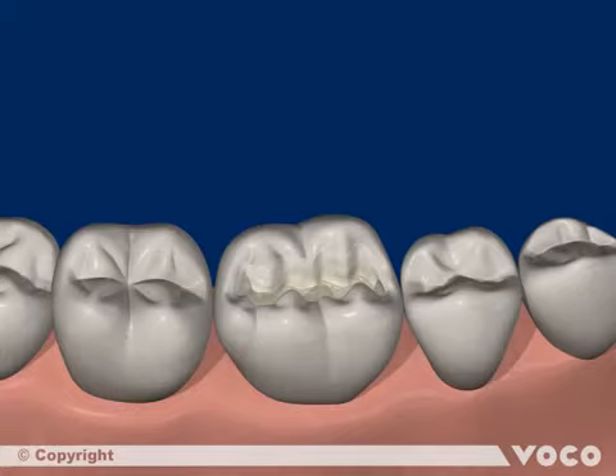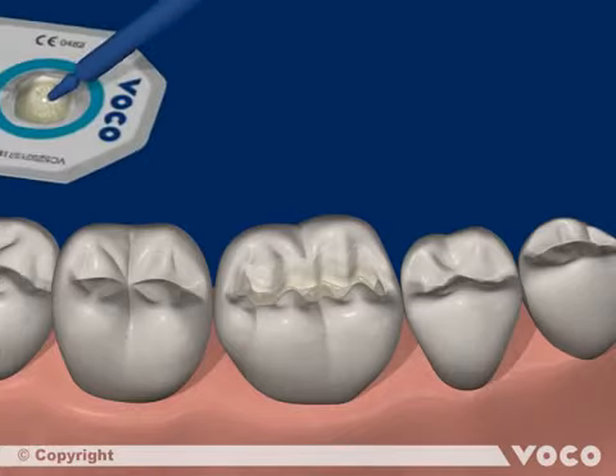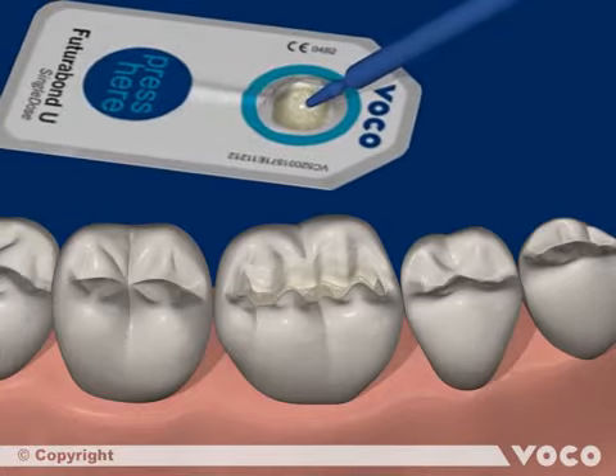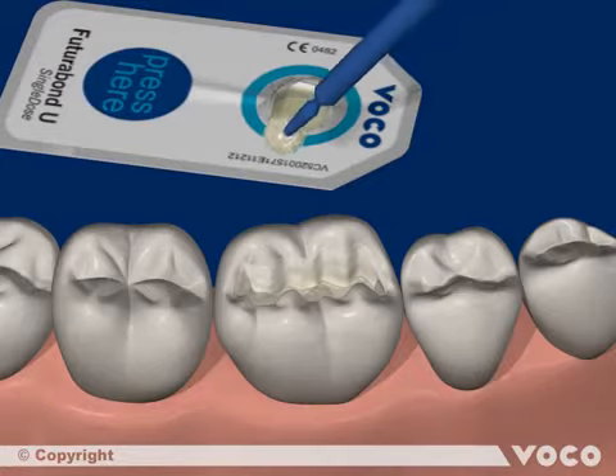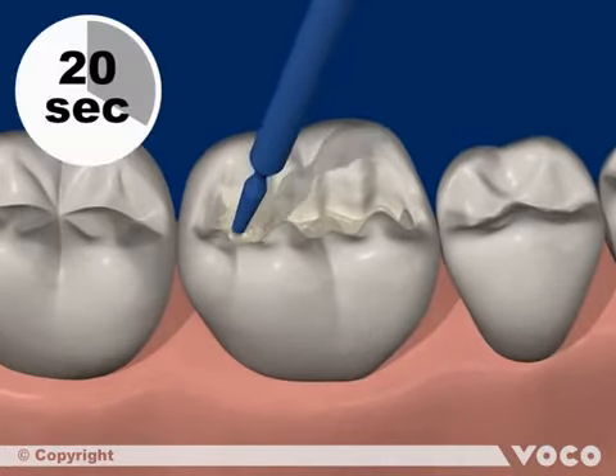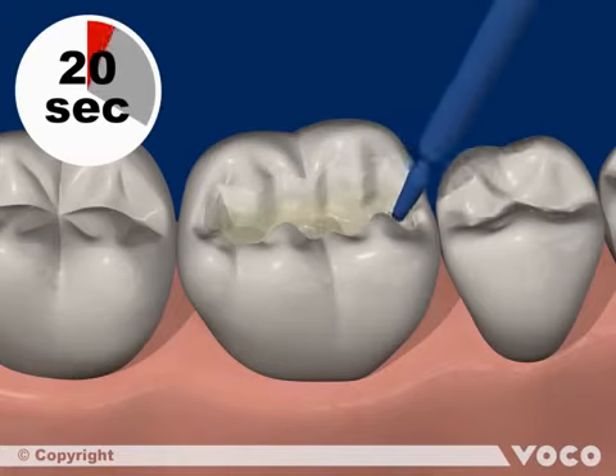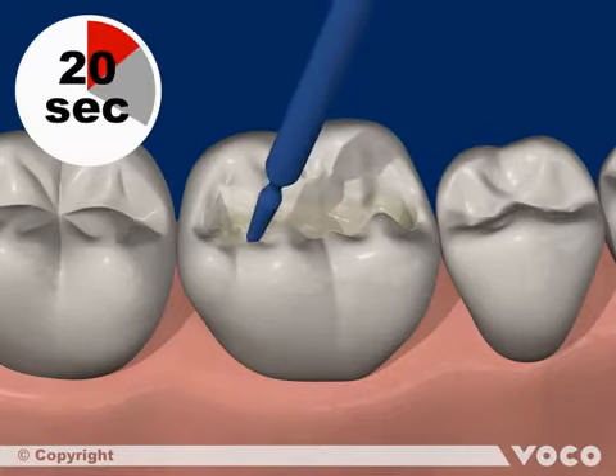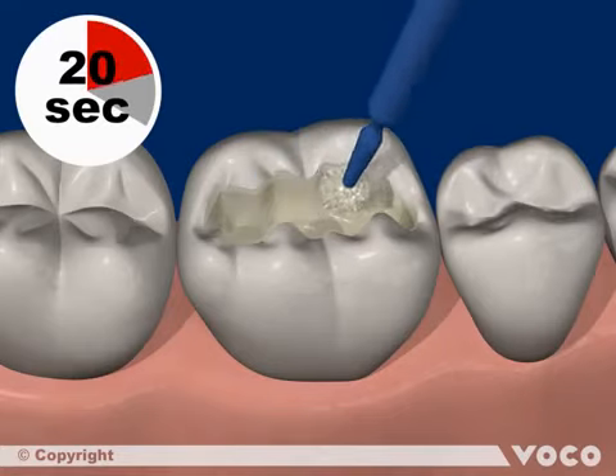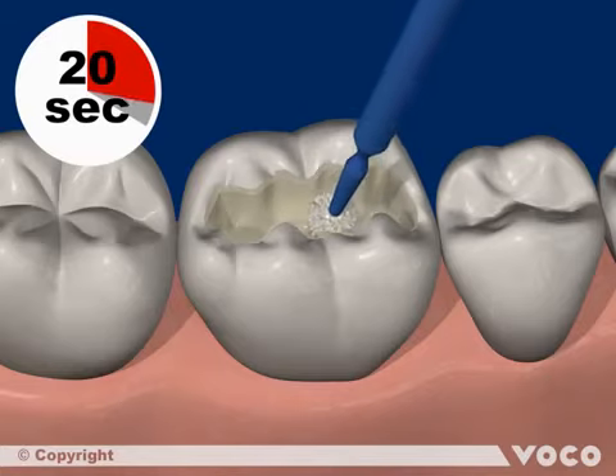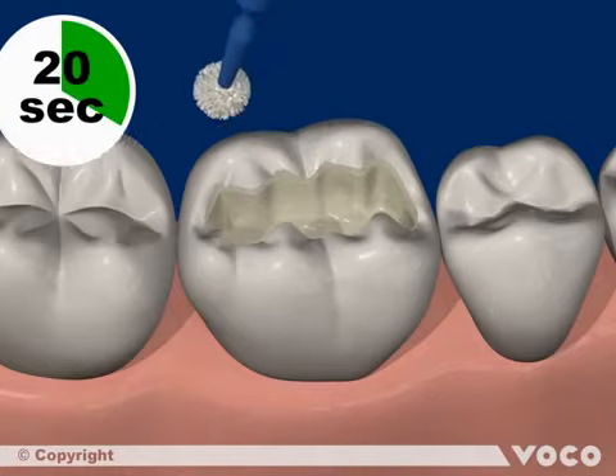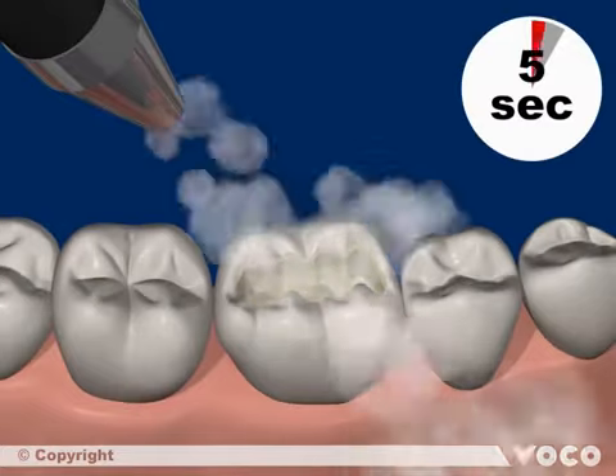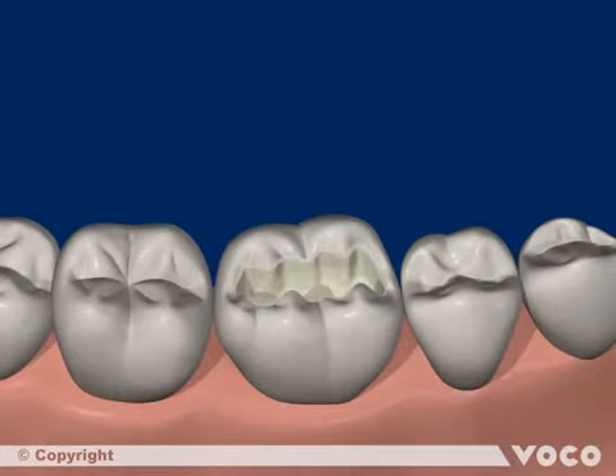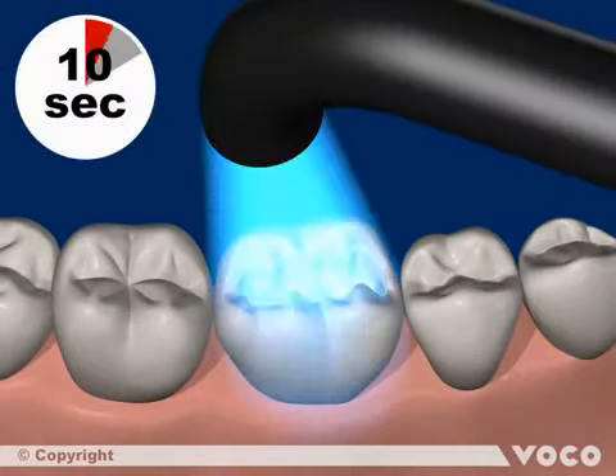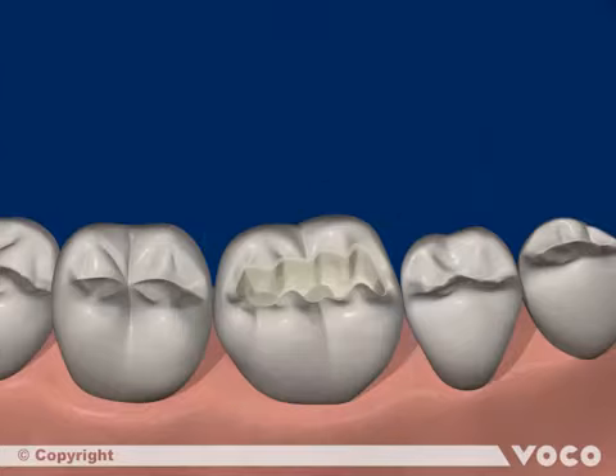Cavity preparation, cleaning and drying are followed by the application of the adhesive, here Futurabond U, which is used in single-dose mode. After activating and opening of the single-dose blister, the adhesive is applied homogeneously to all cavity surfaces and rubbed in for 20 seconds. The adhesive layer is then dried off with dry, oil-free air for at least 5 seconds. 10 seconds of light polymerization are necessary to cure the layer completely.